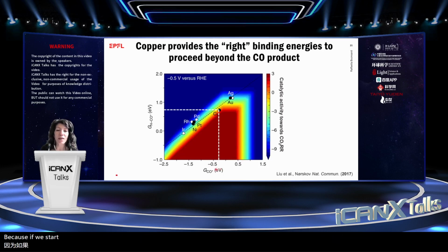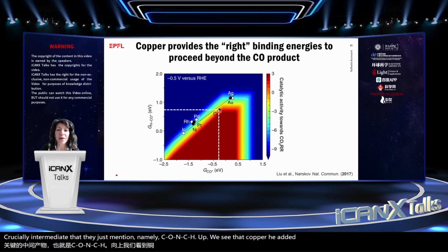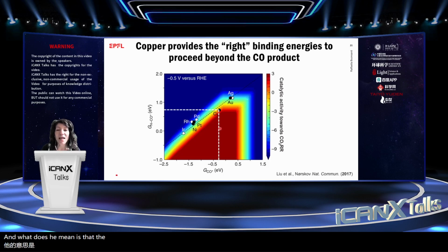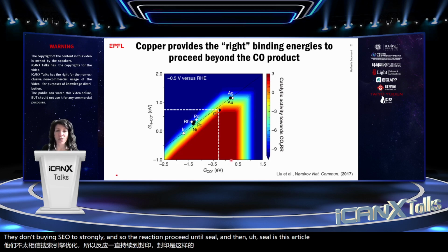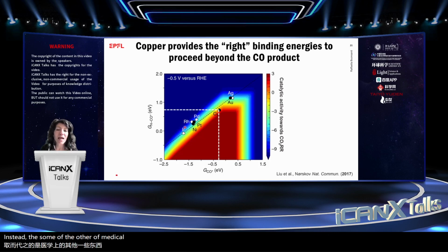Because if we start plotting the binding energy of copper towards some of the crucial intermediates that I just mentioned, namely CO and CHO, we see that copper sits in the middle compared to other metals. And what does it mean? It sits close to this red region, which indicates higher activity towards CO2 reduction beyond CO. Because when we have silver and gold, they don't bind CO too strongly, and so the reaction proceeds until CO, and then CO is desorbed from their surface. Instead, some of the other metals here get poisoned by CO because they bind CO too strongly. So copper emerges as special.